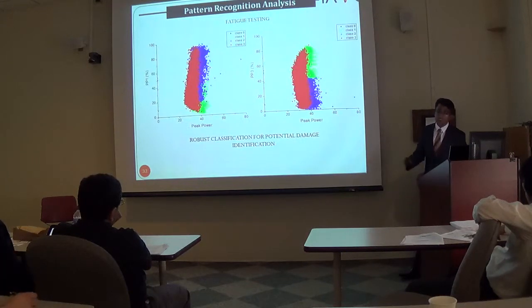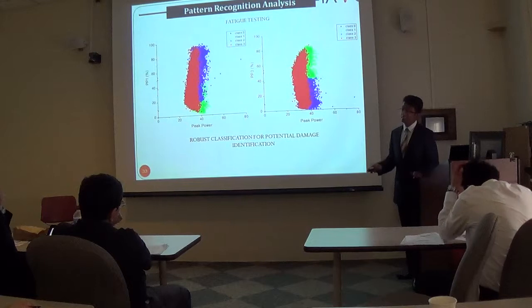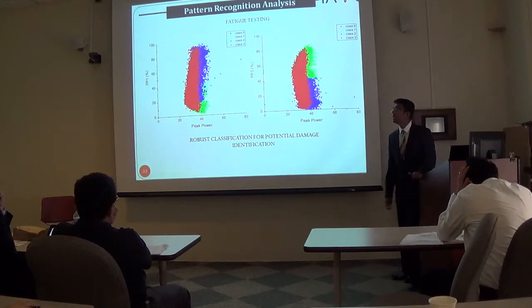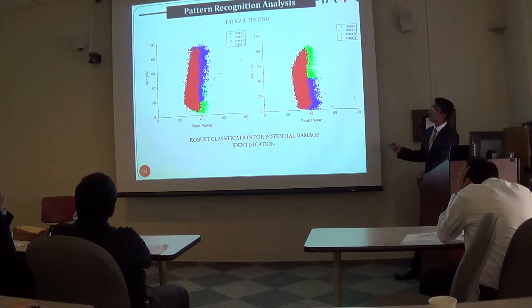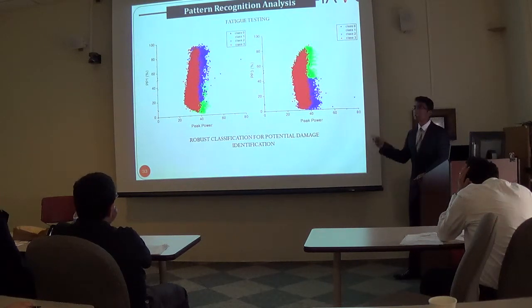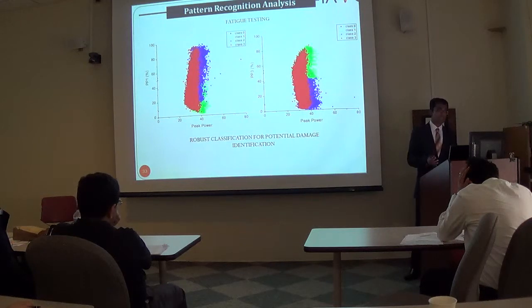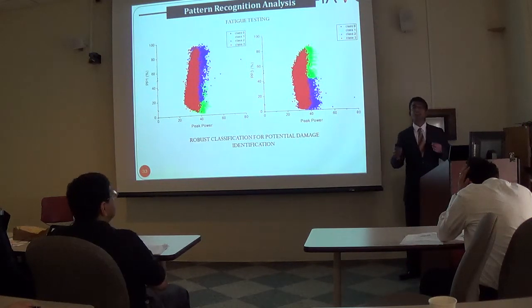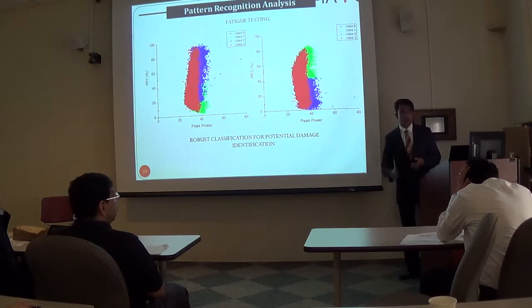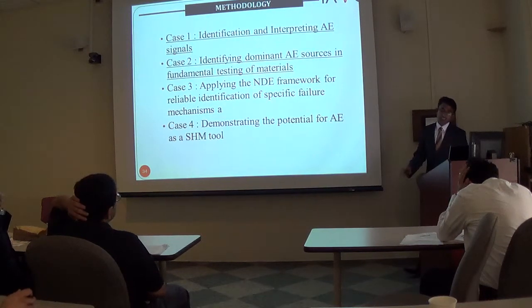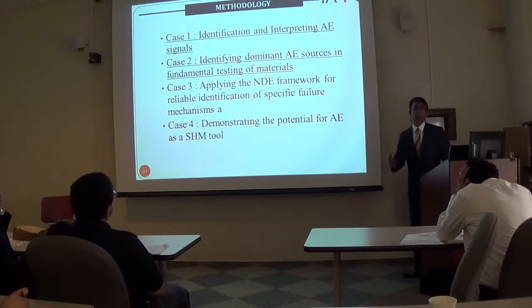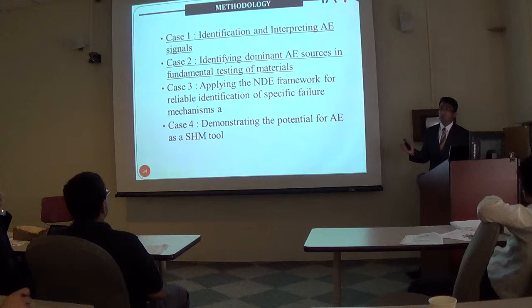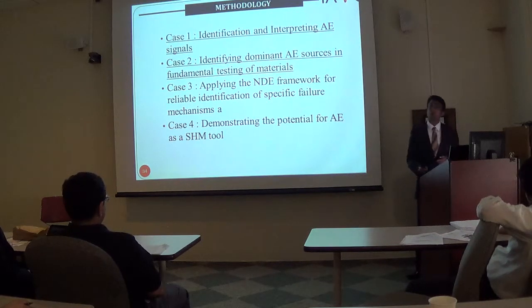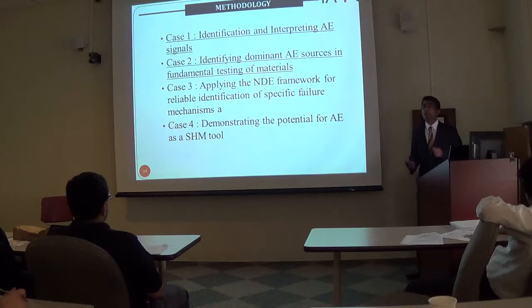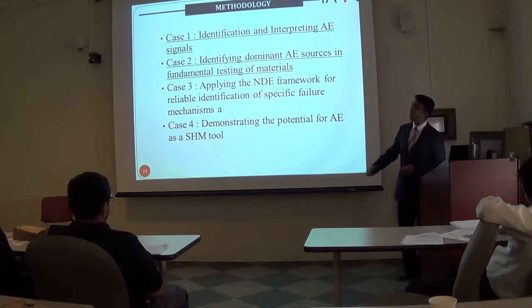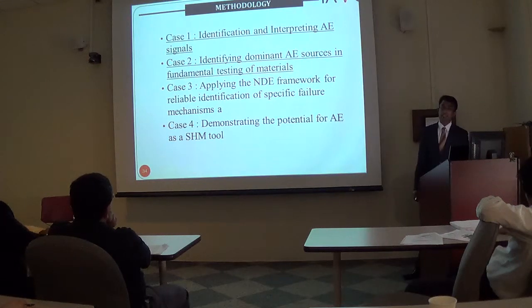Now, the same pattern recognition analysis was then repeated on the fatigue testing of the aluminum alloys, and very similar AE feature analysis characteristics were identified across the different fatigue specimens. Thus, this forms the basis of developing a robust classification algorithm for potentially identifying the damage sources in these kinds of materials, irrespective of the loading conditions. So this framework was then applied to specifically identify targeted failure mechanisms, such as the one specified by the ONR, where it was just to identify the crack initiation in aluminum alloys. So this framework was then applied to reliably identify crack initiation in aluminum alloys.